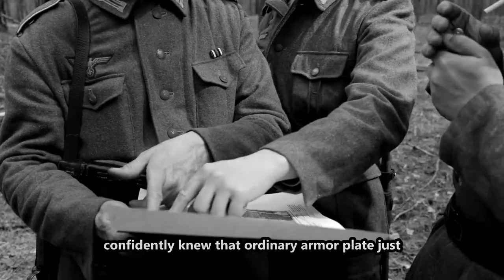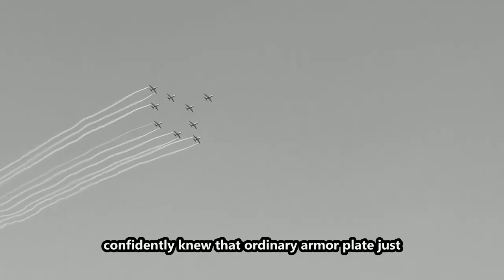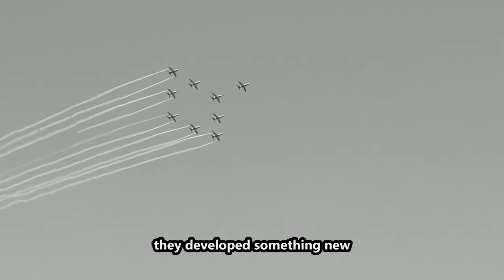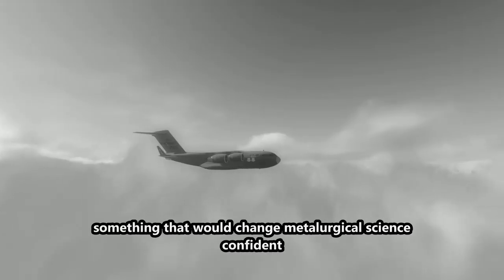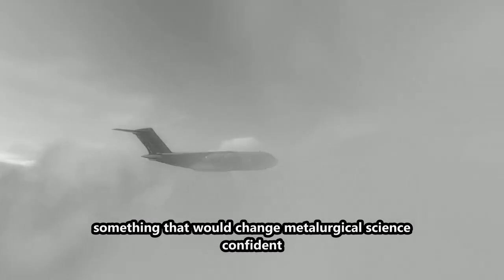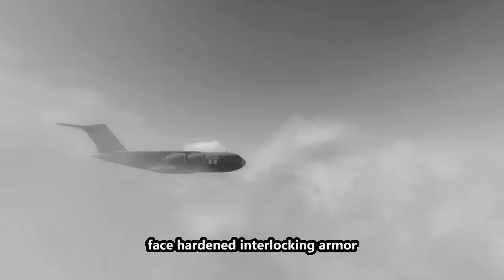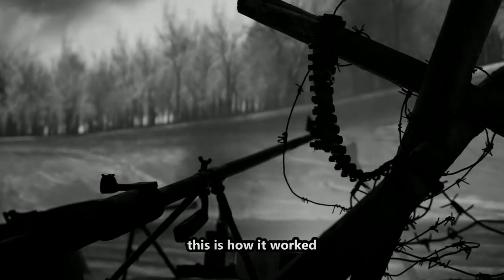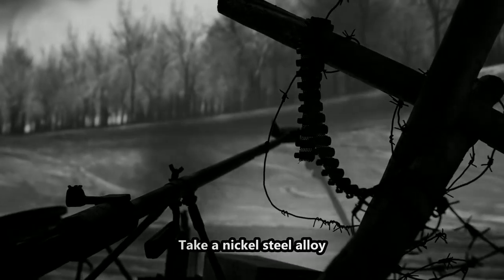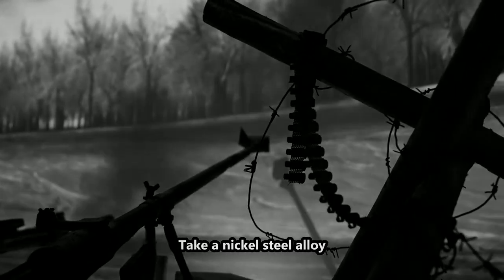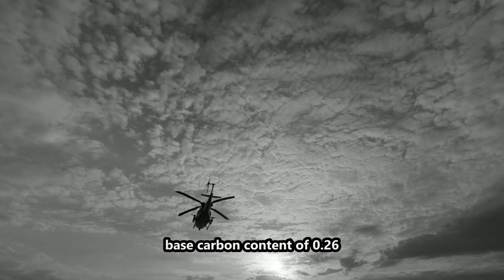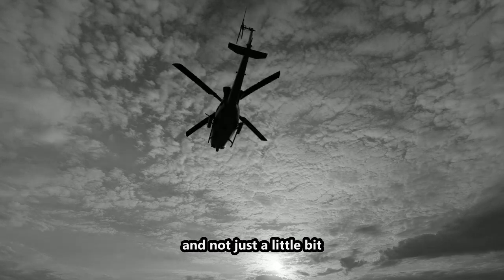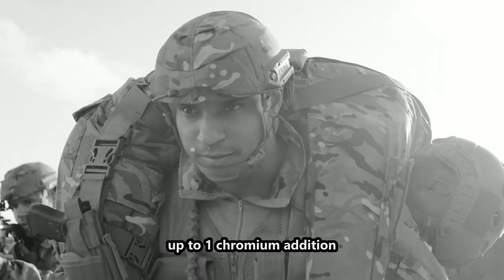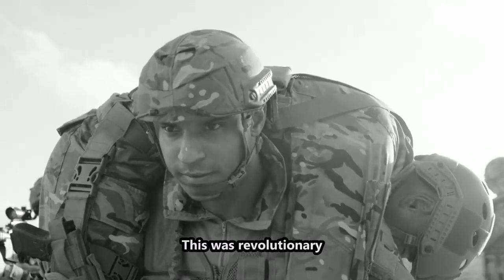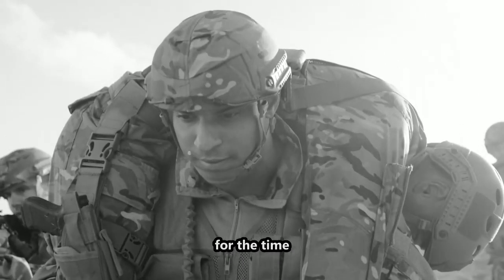Krupp engineers knew that ordinary armor plate just wouldn't cut it. So, they developed something new, something that would change metallurgical science forever: face-hardened interlocking armor plates. Technically, this is how it worked. Take a nickel-steel alloy, base carbon content of 0.26 to 0.35%. Add chromium, and not just a little bit, up to 1% chromium addition. This was revolutionary for the time.